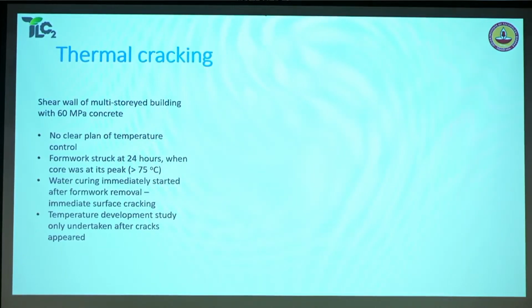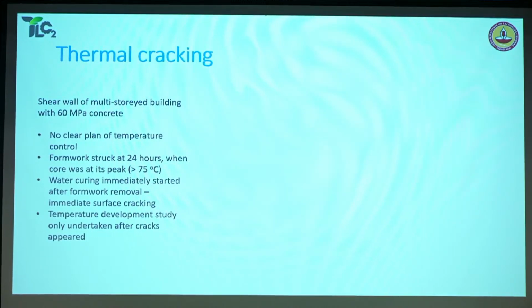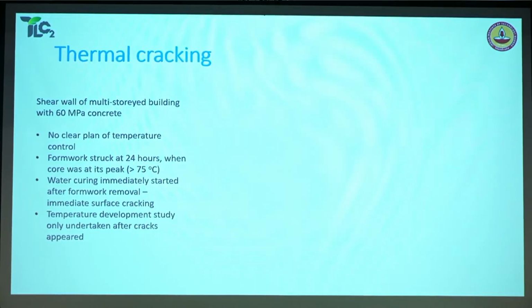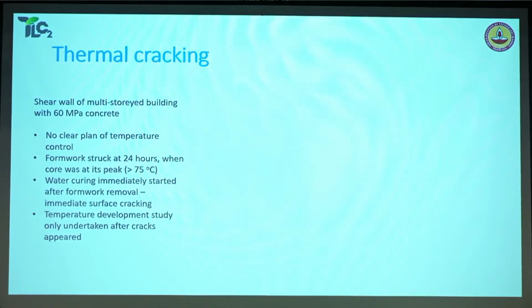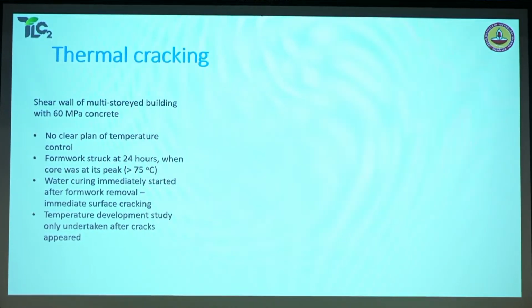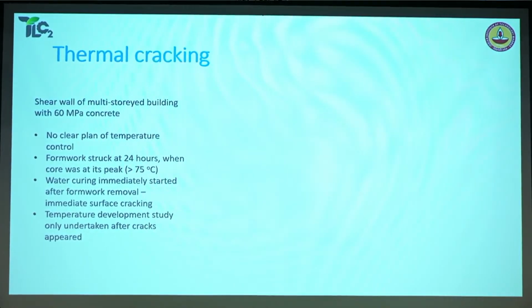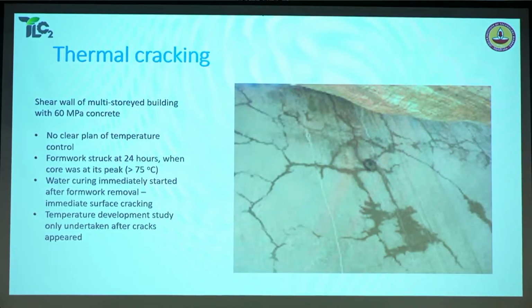Now, here, this is a shear wall of a multi-story building with 60 MPa concrete. There was no clear plan of temperature control in this case. People didn't think about it. They just struck the formwork at 24 hours, just like usual. And at that time, it was actually a peak core temperature of 75 degrees Celsius. But no temperature modeling was done, so they didn't really know what was the peak temperature inside. And as soon as formwork was removed, they started pouring water, and obviously cracks like this appeared. This is a shear wall of a multi-storied building. You can imagine this kind of cracking is not good in a shear wall.